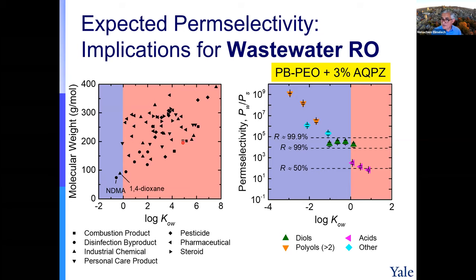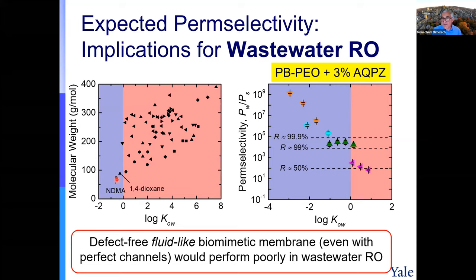And they will go through this membrane because 97% of the membrane is this polymer, and these molecules partition into this polymer and dissolve and then diffuse through it. And we will only remove this hydrophilic compound. So the dramatic conclusion here is that if you create such a membrane, although they are good for seawater desalination, they will not be good for wastewater, because in wastewater, all the contaminants, or most of them, are hydrophobic, and they will easily go through this membrane.